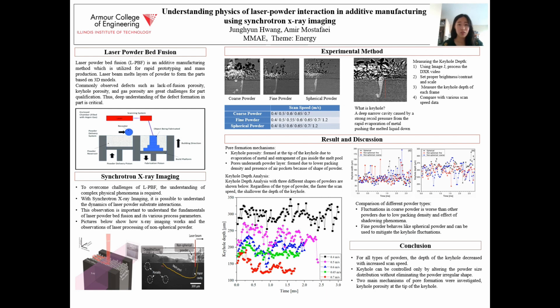From the keyhole depth analysis, as you can see in the graph in the middle, we found out that the faster scan speed results in the shallower keyhole depth regardless of powder shape. Also, more fluctuation of keyhole depth was observed in coarse powder than other types of powders because it has a lower packing density. Finally, the fine powders results were almost the same with the spherical powders and turned out that it can be used to reduce the keyhole depth fluctuations.